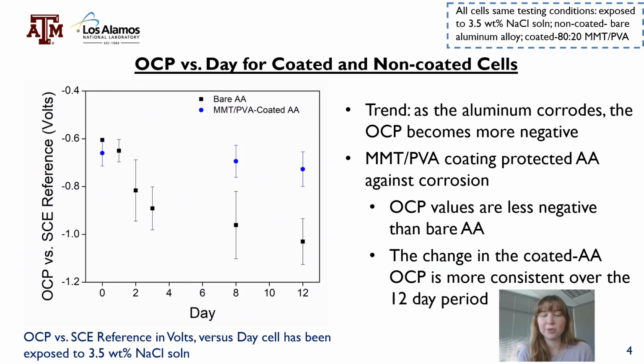Next, we have an OCP versus day graph for the coated and non-coated cells. So the trend you can see with this graph, where the OCP is versus SCE reference in volts, is that as the aluminum corrodes, the OCP becomes increasingly negative. However, we can see that with the blue data points, the MMT PVA coating protected the aluminum alloy against corrosion. This is evidenced by the fact that the OCP values are in fact less negative than the bare aluminum alloy values. In addition to this, over the 12-day period, the change in the coated aluminum alloy OCP is more consistent than for the bare aluminum alloy samples.